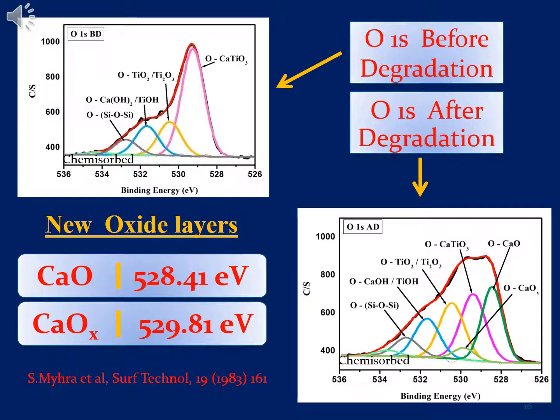Looking at the XPS peak, only focusing on the oxygen 1s peak of the material before I expose it to the prolonged electron beam, and also the oxygen peak of the material which I exposed to the electron beam. I simply refer to them as degraded and undegraded, or before degradation and after degradation. After degradation indicates a material which was exposed to a prolonged electron beam. Now, I'm looking at the binding energies of the material before degradation. Now, what do I see?